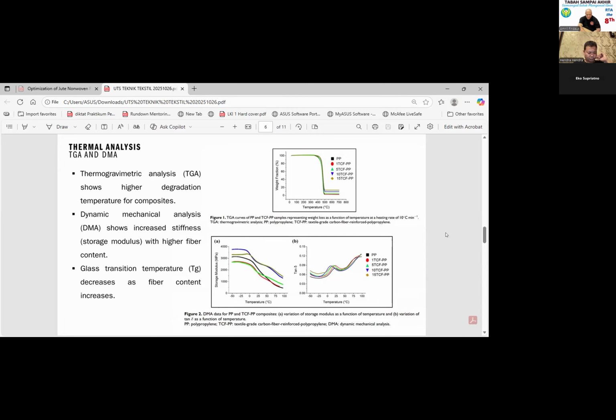In the study, the research found that composite containing carbon fiber degrades at a higher temperature than pure polypropylene itself. So with the addition of the carbon fiber, it degraded at a higher temperature compared to without the TCF. This means that adding the TCF makes the material more heat resistant, which is a good sign, right, for long-term durability. The next test is the dynamic mechanical analysis, or DMA.